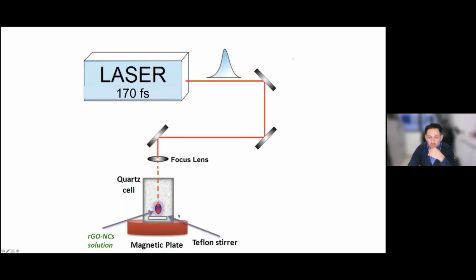This is a quartz cell. When the perovskite nanocrystals are diluted together with reduced graphene oxide flakes, and then we irradiate this mixture of materials under different conditions, upon tuning the conditions, that is the irradiation time, the laser energy, and also the environment, I mean the solvent of the nanocrystals or the RGO, then actually we